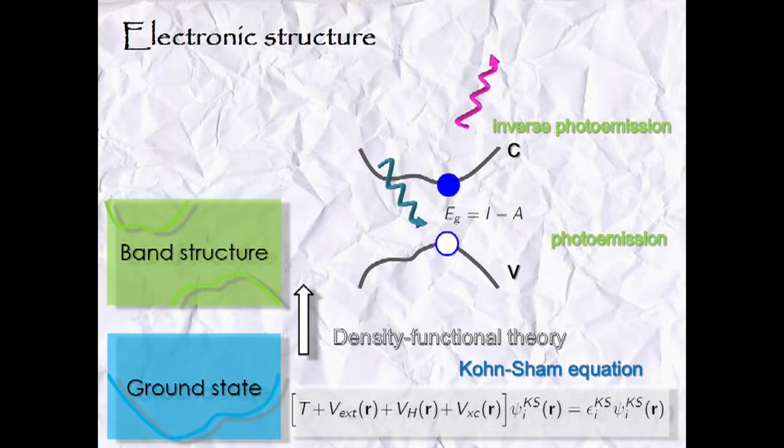So how do we describe this? Obviously, we have to describe not an n-particle system, but a system with a particle going away or coming in. So we have to go to Green's function theory. How does this work? What do we need? We have somehow boiled down the many-body system of interacting electrons to a fictitious system of non-interacting electrons. And since this system was fictitious, we were not allowed to interpret the energies. What we want to have, however, is also in principle, single particle energies that we are allowed to interpret. Because single particle energies are dear to us.